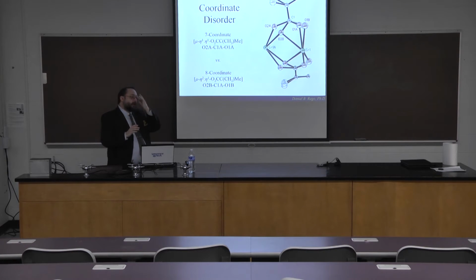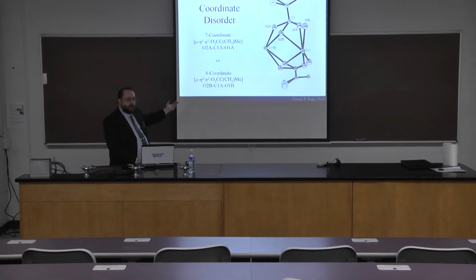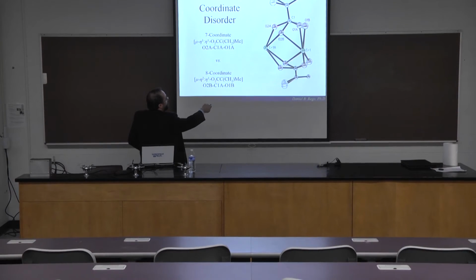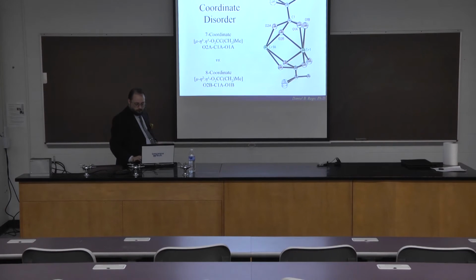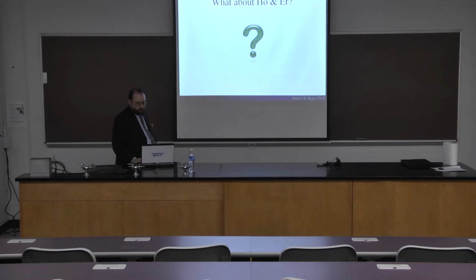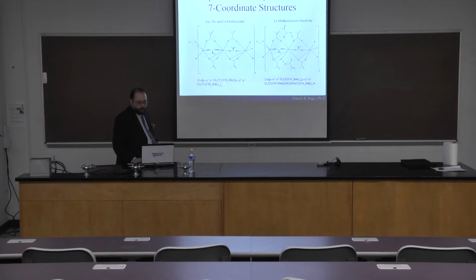Okay. But basically in the crystal structure, we actually located electron density, which is what you're actually measuring with the XRD, in both this conformation, the O2A O1A, and O2B O1B. Well, maybe I conflated the structure with the crystal, but that crystal looked exactly like a system I know about, which is a twin structure. And of course, twinning and disorder can look a lot alike sometimes. So I wondered if you had thought about that, if there was a way to distinguish.